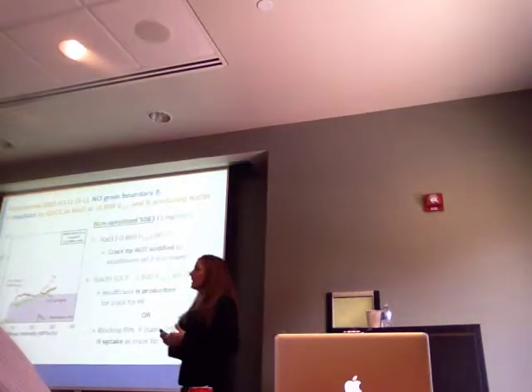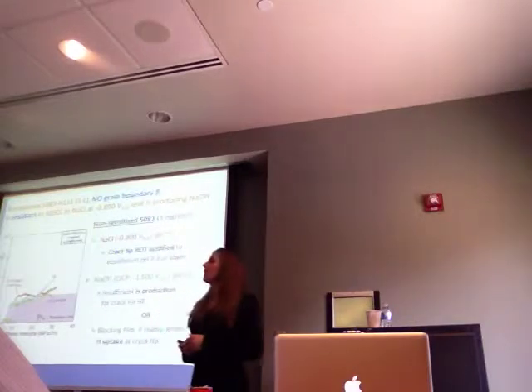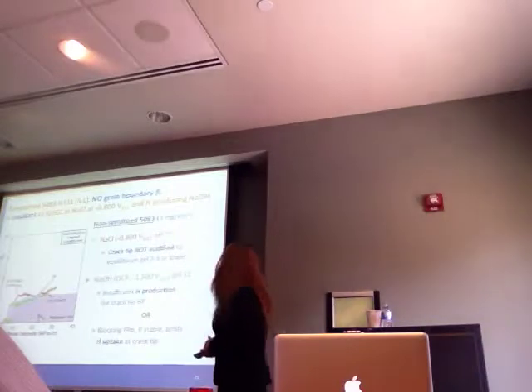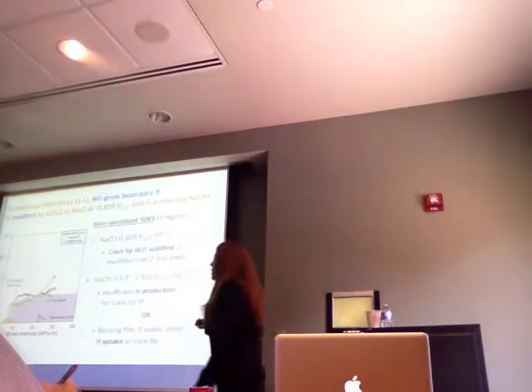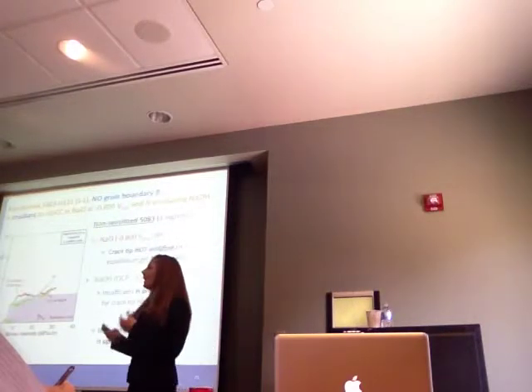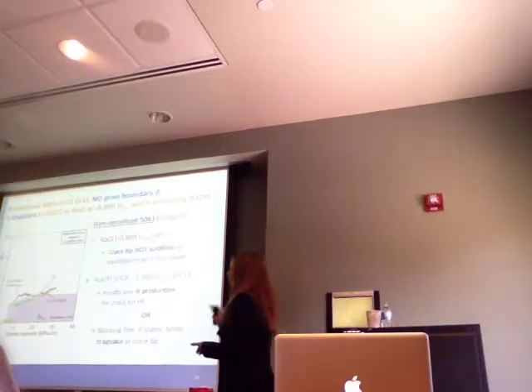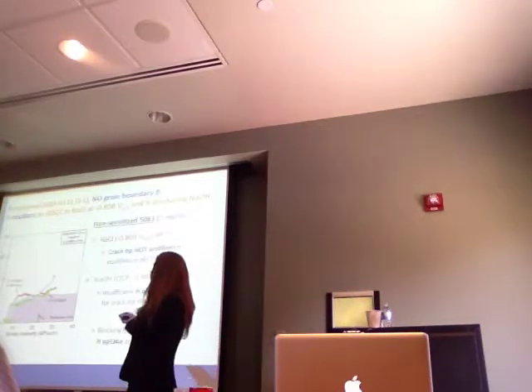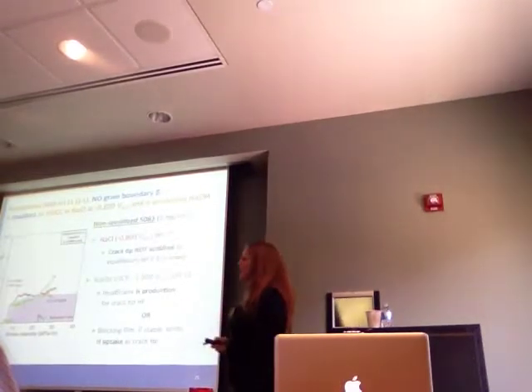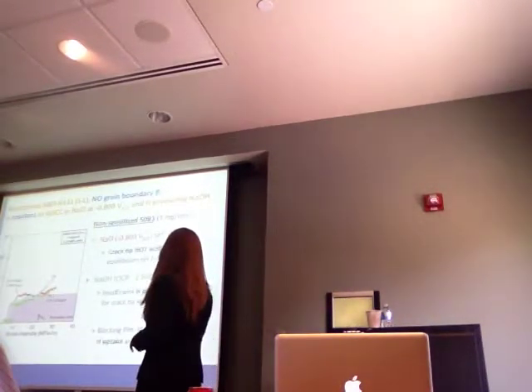And we believe this is because that crack tip acidification is not developed. We are not getting that pH level down to 2 or 3 because we have no beta to cause that dissolution and hydrolysis. So the next thing we decided to do was look at an environment where you have a lot of hydrogen production and that we know causes hydrogen uptake on a bare surface. So we used a sodium hydroxide environment at both open circuit potential and at negative 1.8 volts, very highly cathodic, in a very alkaline solution.